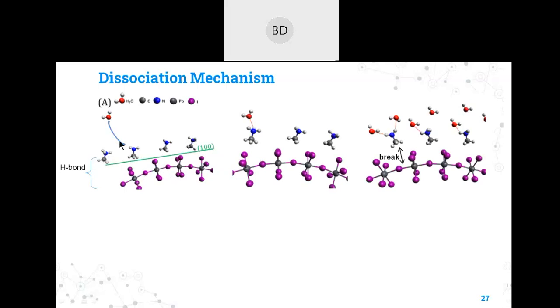So this part already is very hygroscopic in nature. Once the moisture attacks, it starts making some kind of bonding with methyl ammonium. Why? Because H2O is a polar solvent. This is also polar in nature, so it can make a hydrogen bond here itself. And this hydrogen bonding is shown in the FTIR spectra as well. But the property of hydrogen bonding is such that it can have more than one bond at a time. When you increase the concentration of H2O molecules here, it starts taking up the methylamine, because this bonding is more preferable because of the hygroscopic nature of the methyl ammonium, and eventually the bond between methyl ammonium and the PbI2 starts breaking off.